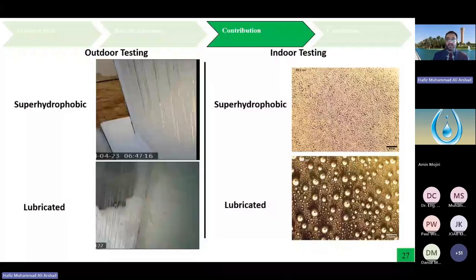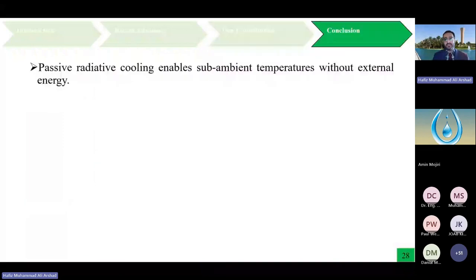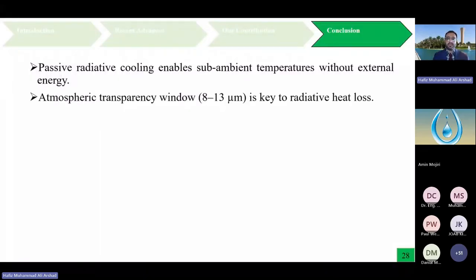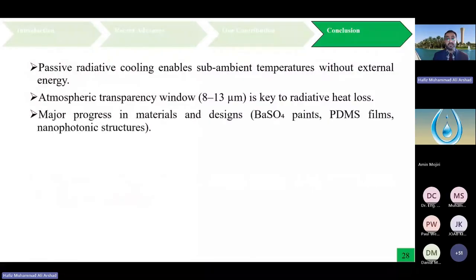Then what is the conclusion on the work? The passive radiative cooling enables sub-ambient temperature without external energy. The atmospheric transparency window is the key parameter, and it should be in between 8 to 13 micrometer to have radiative heat loss. Major progress in material and design, for example, barium sulfate paints, PDMS films, and nanophotonic structures, can now be used in order to get radiative cooling and the use of them in air water harvesting.